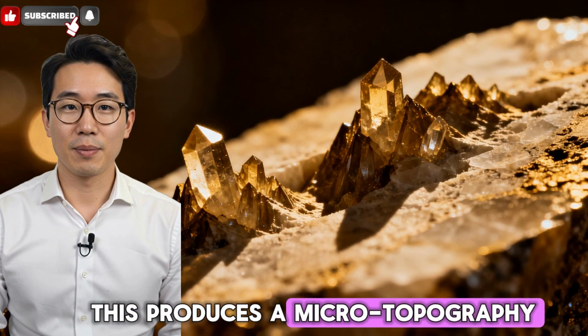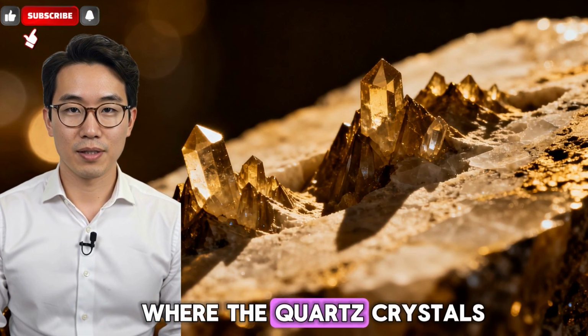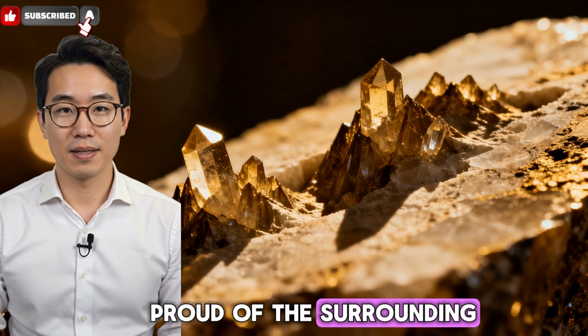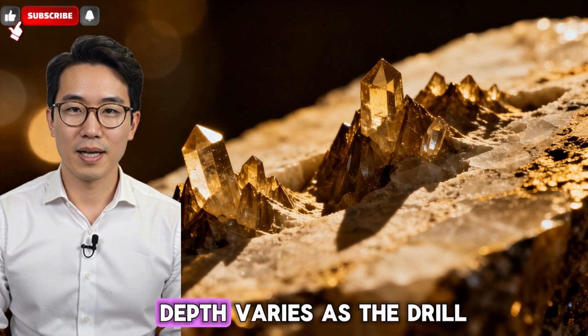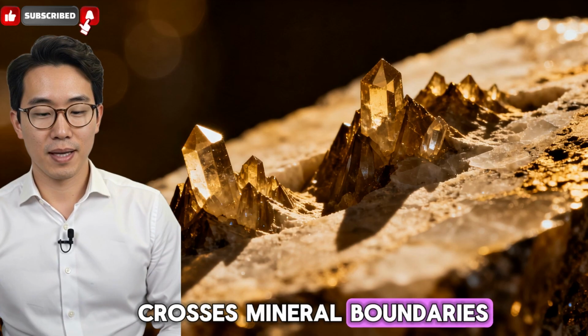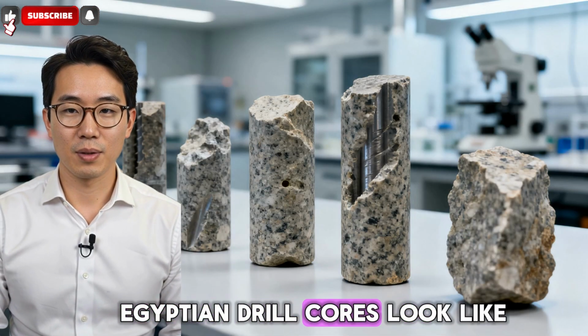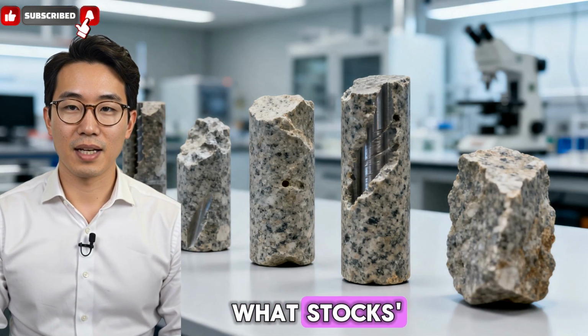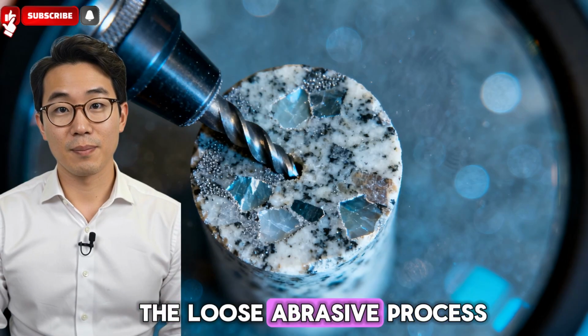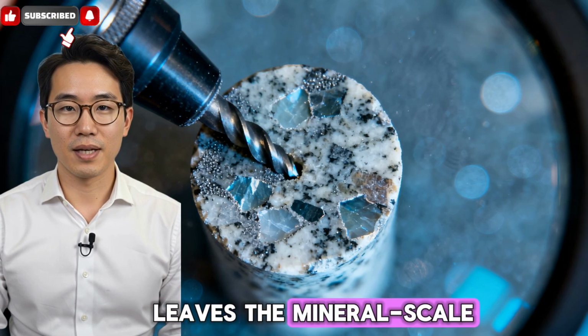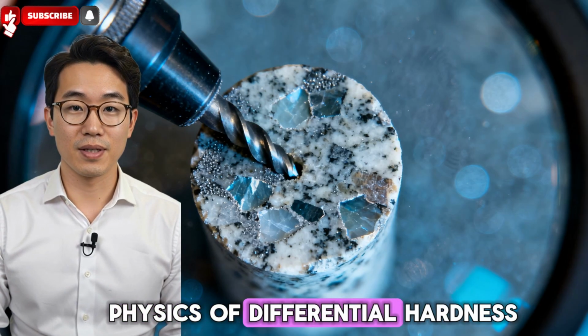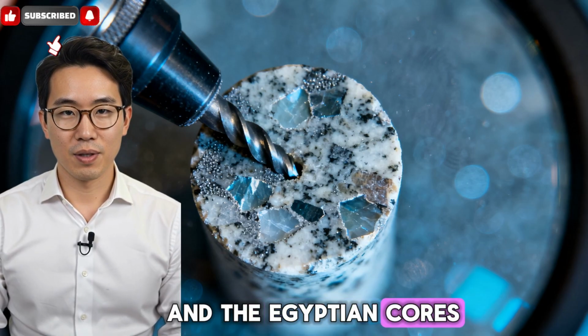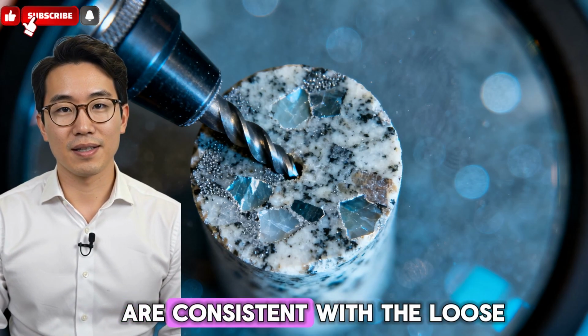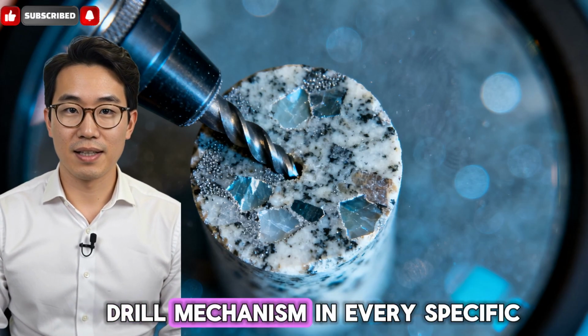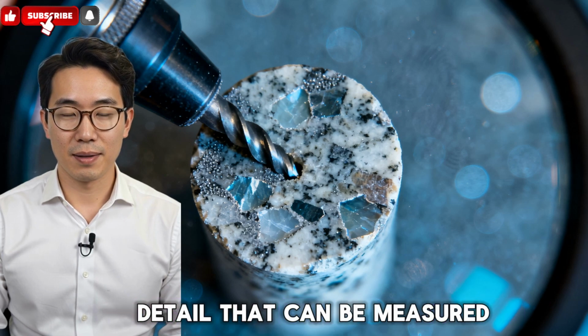This produces a microtopography on the core surface where the quartz crystals stand slightly proud of the surrounding feldspar matrix, and where the groove depth varies as the drill crosses mineral boundaries. This is what most Egyptian drill cores look like, and it is exactly what Stocks's experiments reproduce. The loose abrasive process leaves the mineral scale fingerprint predicted by the physics of differential hardness, and the Egyptian cores that show this fingerprint are consistent with the loose abrasive copper tube drill mechanism in every specific detail that can be measured.